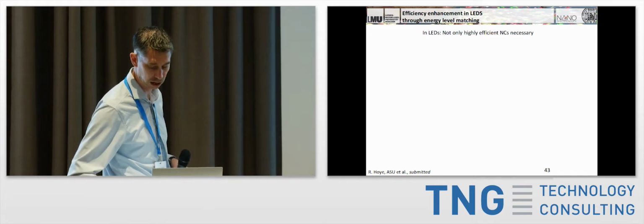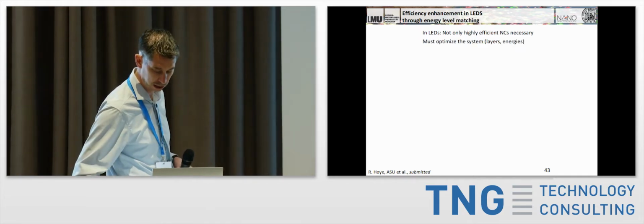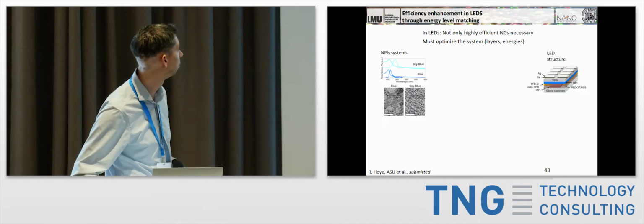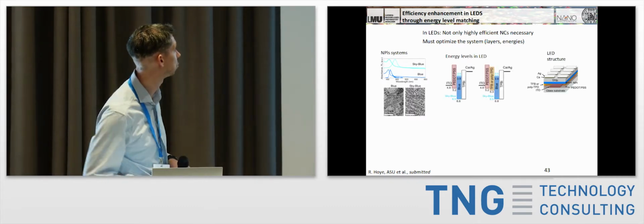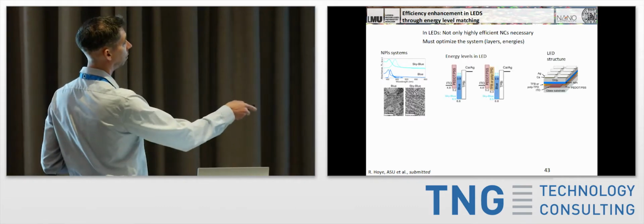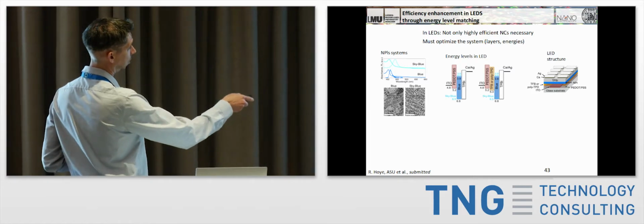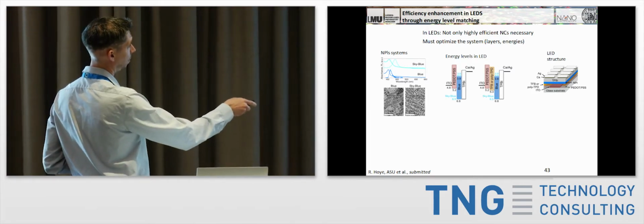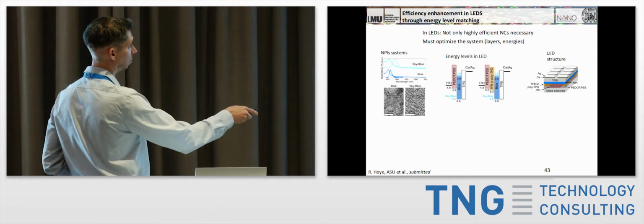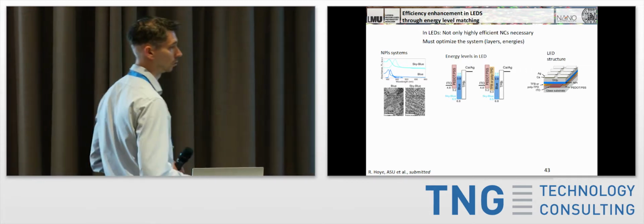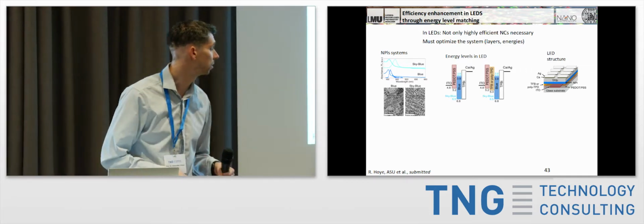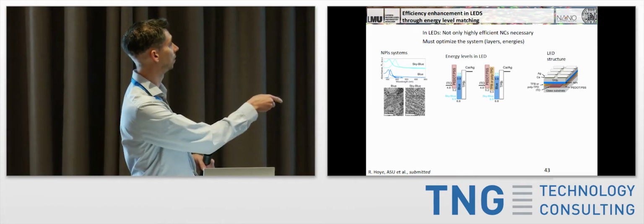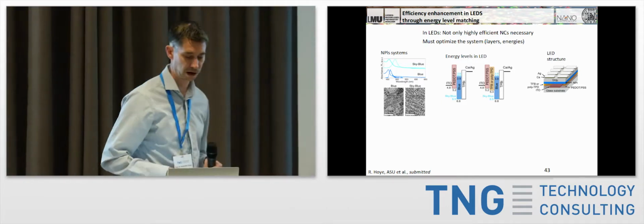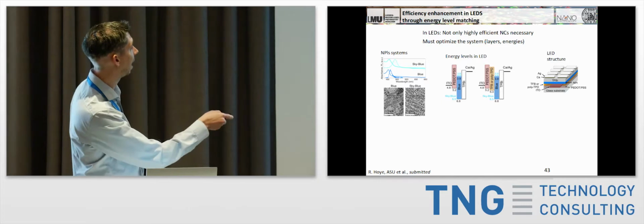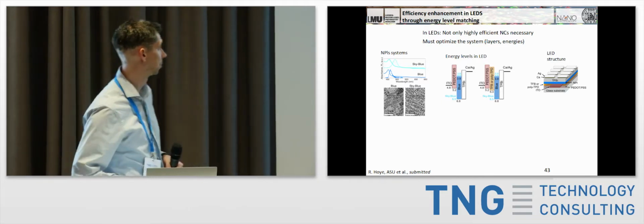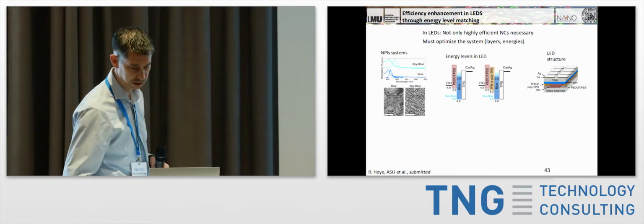And so we figured out, okay, it's not only the quantum yield that we need to take care of, but we need to also look at the actual device structure. So I'm not going to go into too much detail, but one of the big problems here is that as we're injecting charge carriers, there's a huge drop-off from the hole transporting layer into the perovskite, where it's really, really difficult to actually get these holes to go into the emitter layer. And so they're essentially sitting right here at this interface and recombining non-radiatively. So we've been working on adding additional layers into there to enhance the efficiency of these devices.